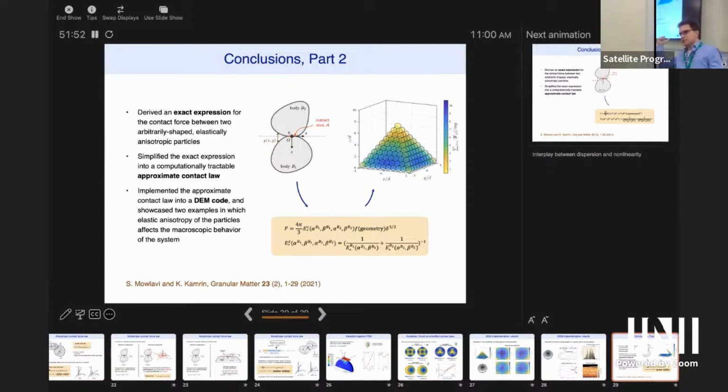And then you can use Hertz's relationship, because once you've got the shape of that gap function, it'll convert that to an effective radius. And that's the thing that goes into Hertz's relationship. So Hertz's relationship, the only hard part is this. But if you know what the gap function looks like, because you create it on the fly, then you can run Hertz. So if it's isotropic but weird shapes, where they touch, you can create an effective curvature, and then you just throw that into Hertz, and that'll work.